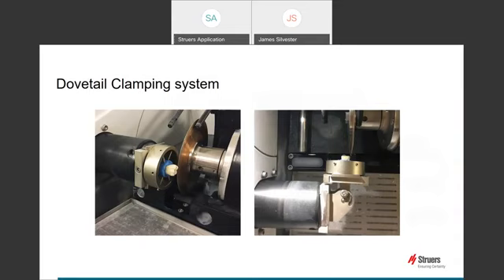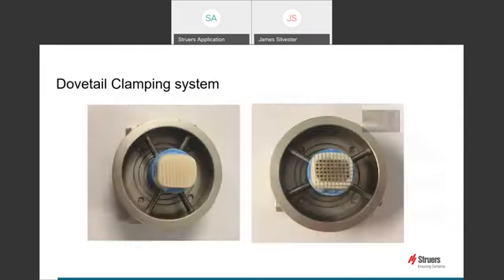On the left, we can see the tooth in its acrylic mounting compound clamped in a dovetail clamp. The image on the right shows the same clamp used in conjunction with the angled clamp to allow us to cut directly into the face of the tooth. The clamp was positioned so that we could cut using the multi-cut function to get accurate, perfectly positioned slices in both the X and Y direction to make very small matchsticks of tooth. The image on the right clearly shows the level of accuracy we can achieve even with a difficult to hold sample such as this tooth.